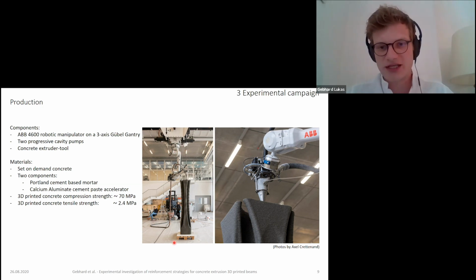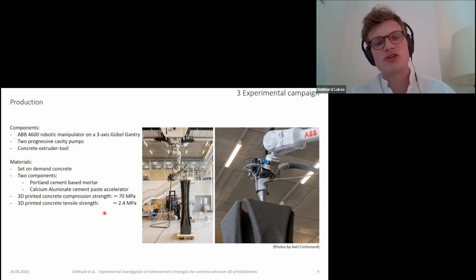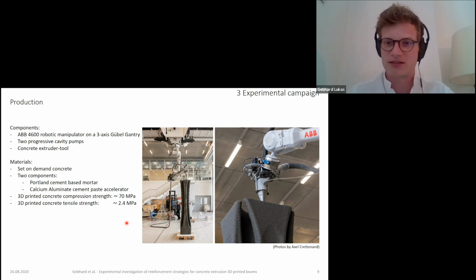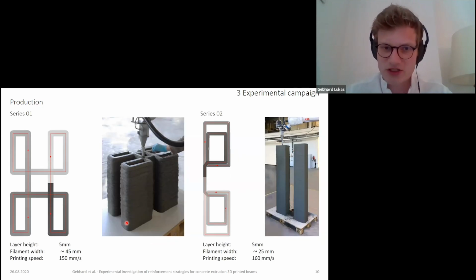And just to say, this is just an exemplary column. These are not the beams that we tested. And we also tested the compressive and tensile strength of the concrete, which was around 70 and 2.4 megapascal respectively. And then we used this system to actually print our beams.